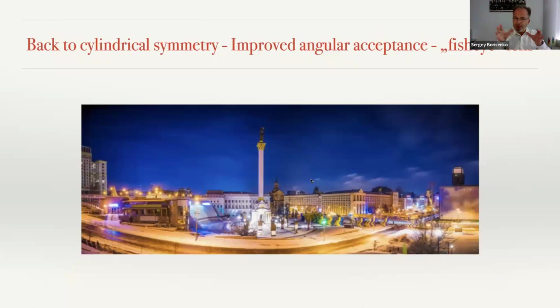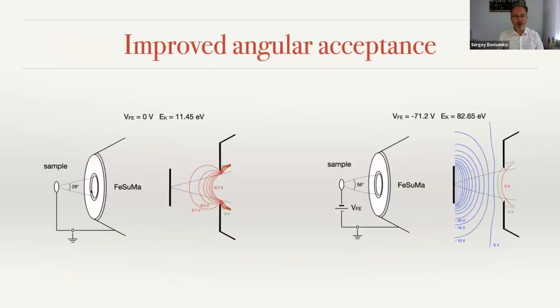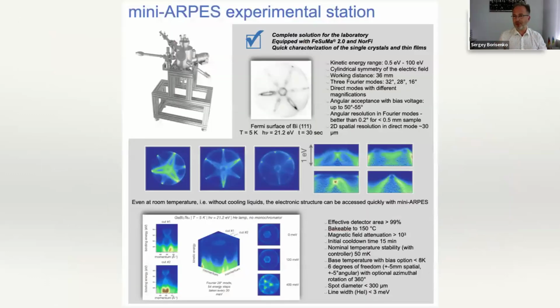One can come back to cylindrical symmetry and use the fisheye effect. If you photograph with a fisheye lens, you can capture more, as in this nice example. So one could apply a potential to the sample, increase angular acceptance, and everything remains cylindrical, with the data set spherical. You are in angle-resolved photoemission spectroscopy.